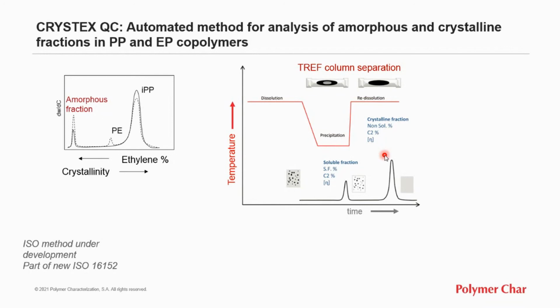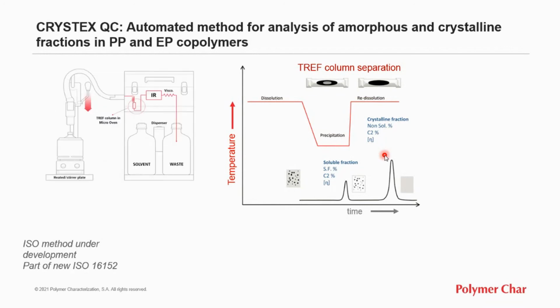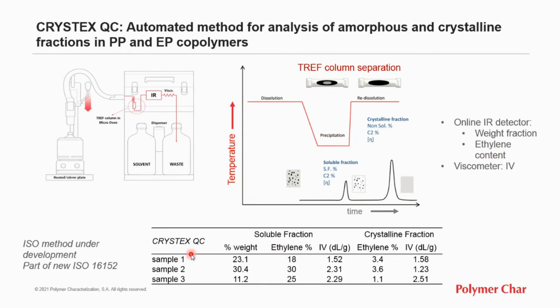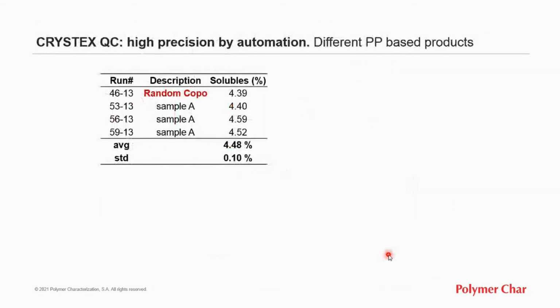After the column, which sits in a micro oven, there is an IR detector and online viscometer. So in this automated analysis, the amount of solubles is determined, but also the ethylene content and the intrinsic viscosity of the solubles and the crystalline fractions, as well as the bulk material. So we can see here the results obtained for different samples: the amount of solubles, the ethylene content, the intrinsic viscosity, and also the crystalline fraction.